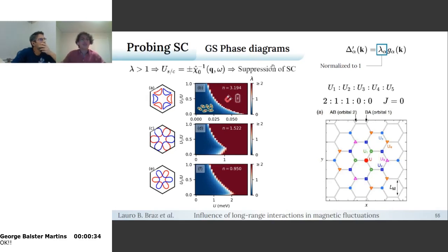And now what I would like to point out is this progression under types of quantity of doping. So in twisted bilayer graphene, we do have up to 8 electrons per site in an effective modeling, and what I'm taking here are only hole doping chemical potentials. So for this first case here, for this n closer to the zero energy, the half filling, which will be n equals 4, it is placed exactly at a Van Hove singularity, and at this value, with this Fermi surface, what we observe is a continuous suppression of the superconducting state as you increase the long-range interactions.